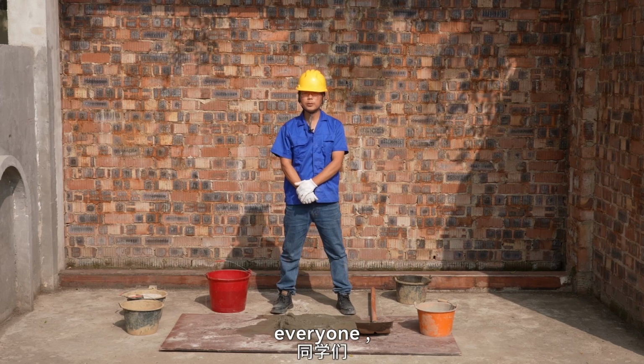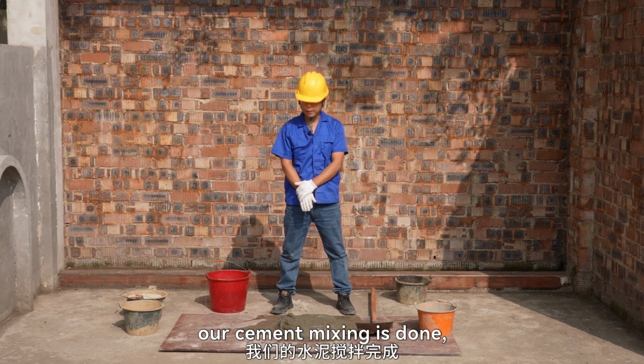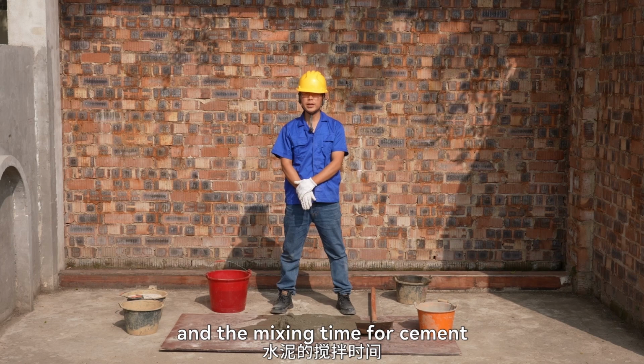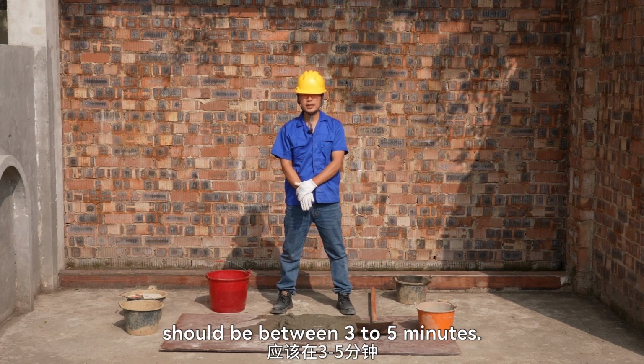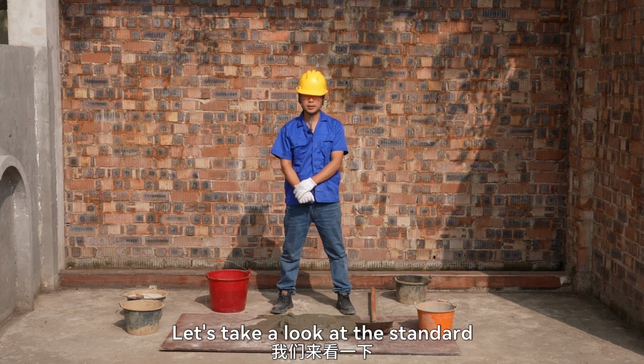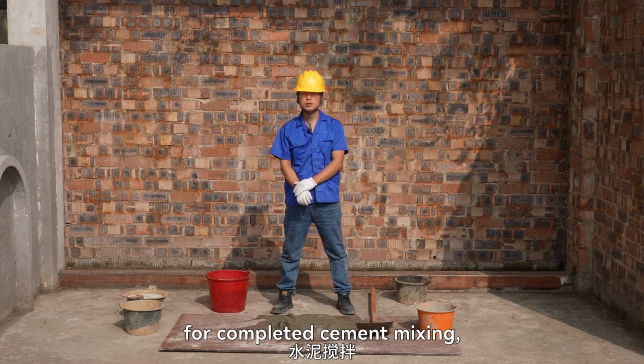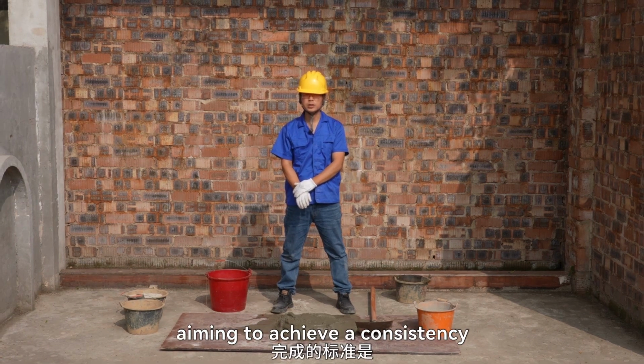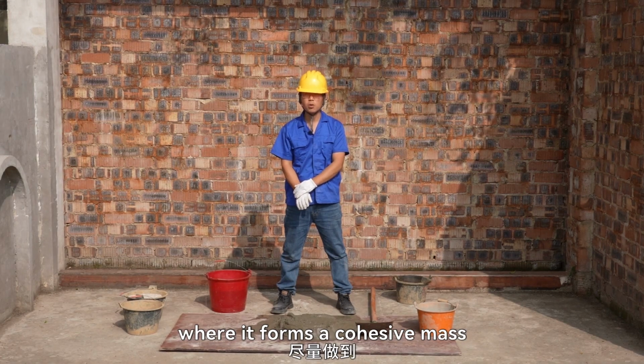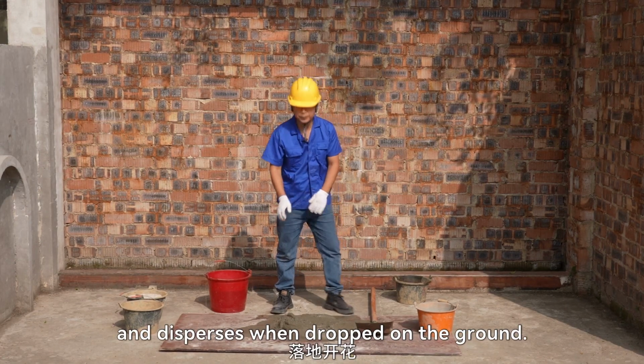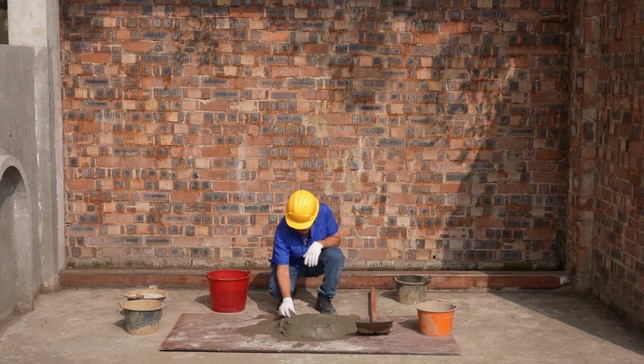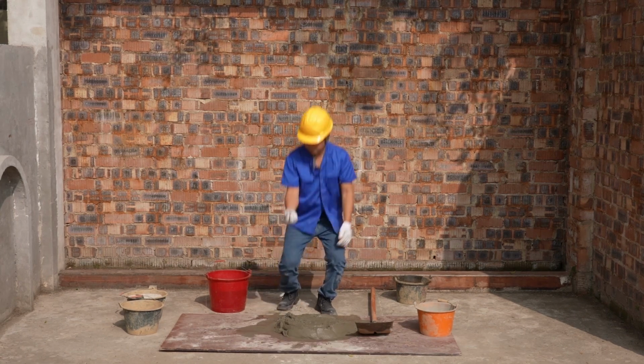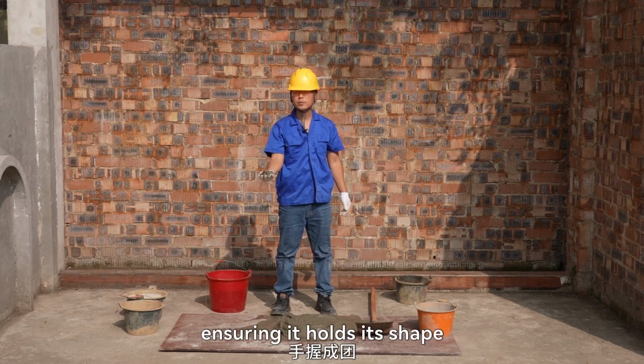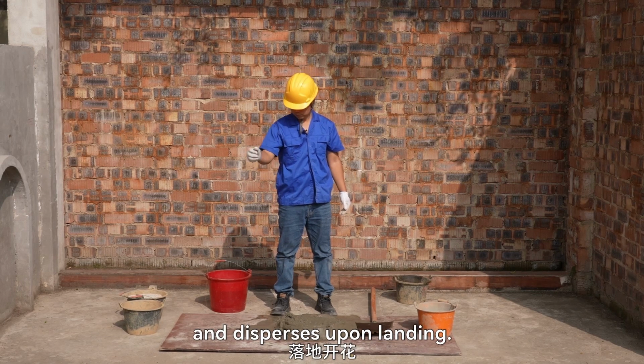Alright, everyone, our cement mixing is done, and the mixing time for cement should be between 3 to 5 minutes. Let's take a look at the standard for completed cement mixing, aiming to achieve a consistency where it forms a cohesive mass when held in your hand and disperses when dropped on the ground. Let's test it now, ensuring it holds its shape without flowing and disperses upon landing.